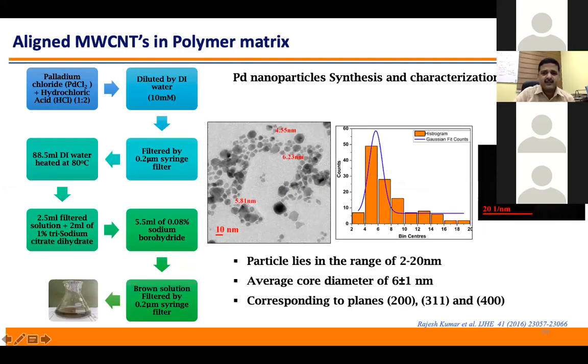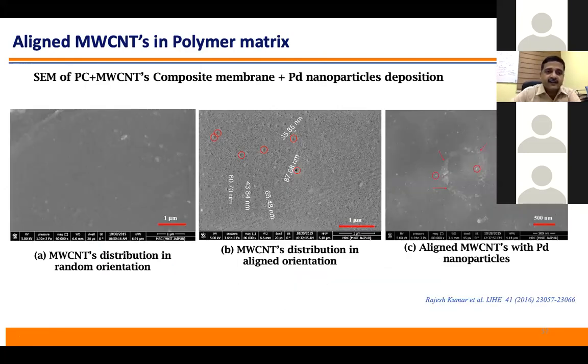So here you can see the particle size is 6 or 7 nanometer. And these 6 nanometer particles are within the nanotubes. And this is the random orientation. And here you can see some dots. So basically this is the opening of nanotubes on the surface. And here we use this palladium nanoparticle also. So this white part is basically the palladium over the surface.